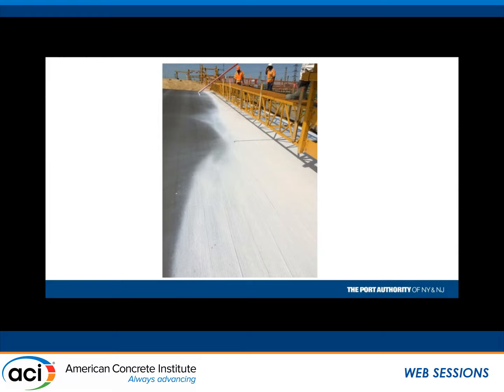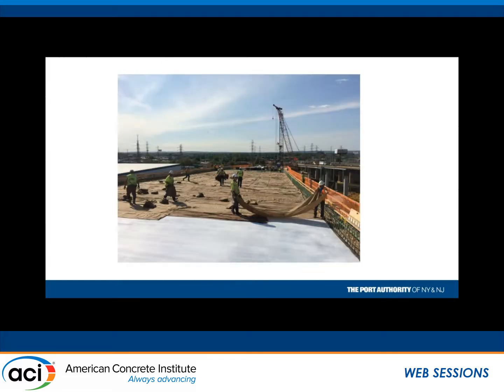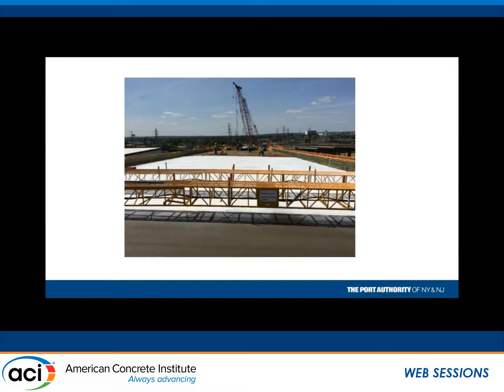And here's our curing method. We put the curing membrane down first. As soon as the sheen has left the surface, we want the curing membrane put down. And the curing membrane acceptance is the entire surface has to be white, just as you're seeing in this slide. And then once we get final set and we can walk on it without marring it, then we put the water curing on there. I'm not sure how important this water curing is anyway, but we did water cure it.